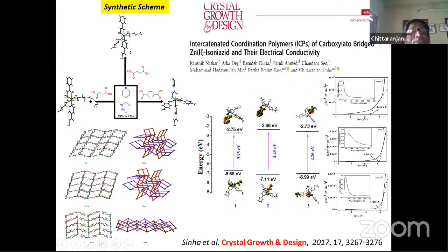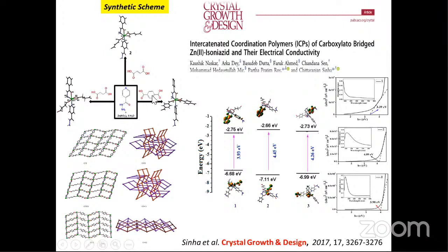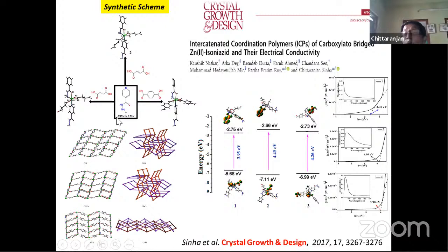Herein we changed the carboxylate bridging group, with reference to the succinic acid, fumaric acid, and also 1,4 benzene dicarboxylic acid, with zinc as the node. That is, the metal center, instead of cadmium in the previous one, we use zinc using 3 different types of carboxylates, while isoniazide is the same. And this leads to three different compounds. These three different compounds have different barrier heights, and this barrier height leads to a different conductivity pattern. So the metal remains the same in three molecules. Only the bridging carboxylates are changed.